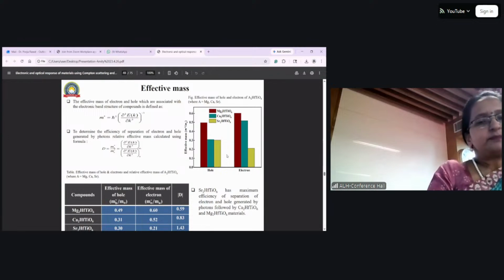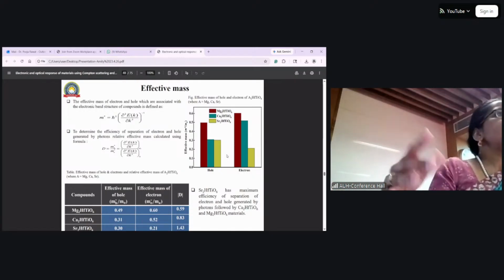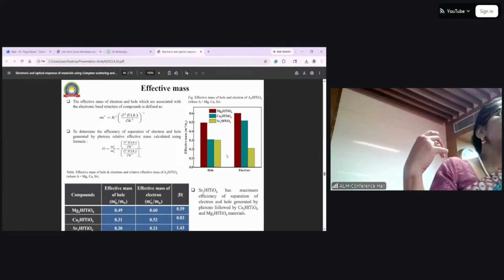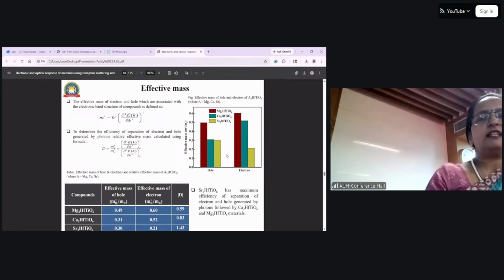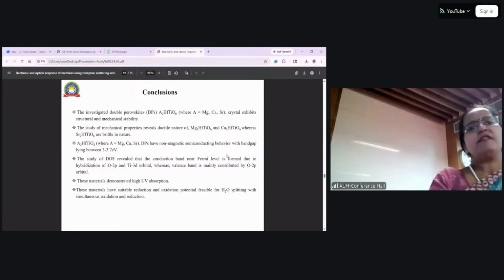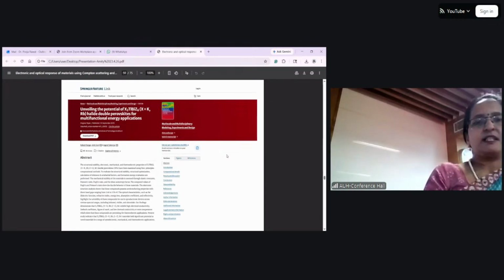Then we checked the effective mass and the efficiency of separation of the electron and hole, because if I incident some light, an electron-hole pair will be generated. If they recombine again, if they won't be able to travel a large distance, it will be wasted. They won't do any kind of application. So if I want them to split my water, they should travel a large distance. So we checked their effective mass and their D value, and it was quite large, higher than the required value. So I am just skipping the remaining things.